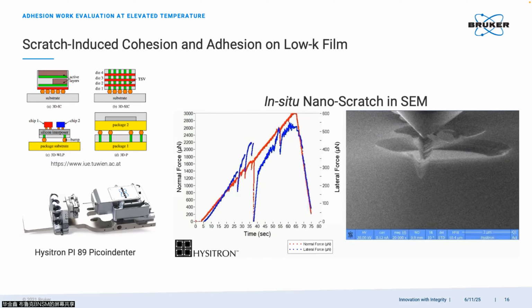For example, if you look at the normal force, which is the blue dots, you will find there are actually two different behaviors of, I would say, cracking. The first one is these two small ones. Actually, the cracking happens within the top layer itself. So it is what we call cohesion, which are cracking events that happen in the top layer only. So it is not the interfacial debonding.